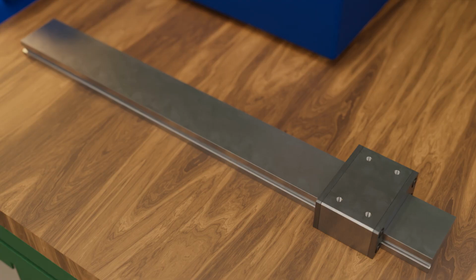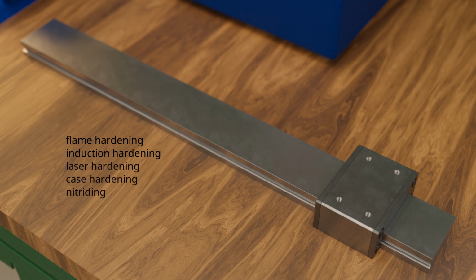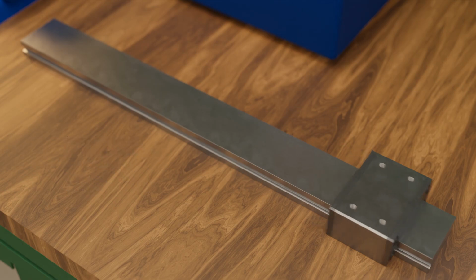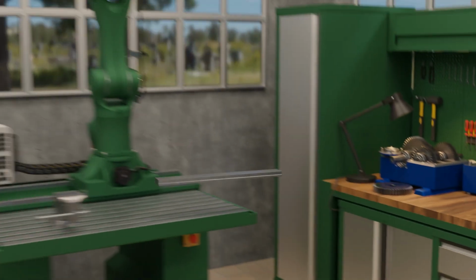Depending on the type of surface hardening, there are different processes such as flame hardening, induction hardening, laser hardening, case hardening, or nitriding. With the exception of nitriding, the increase in hardness of all surface hardening processes is based on microstructural changes during heating and subsequent quenching, as in normal quenching and tempering. More information can be found in the linked video. Let's first take a closer look at flame hardening.